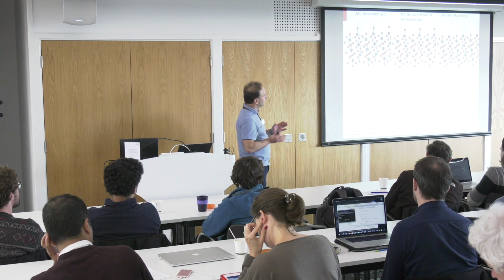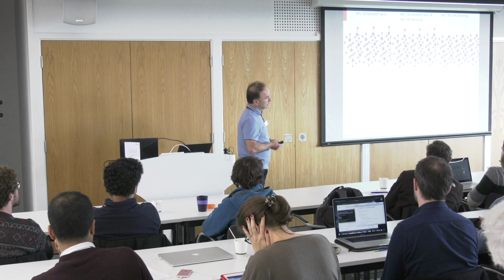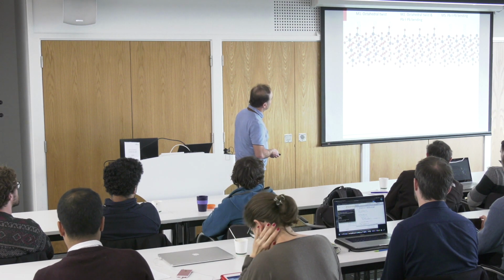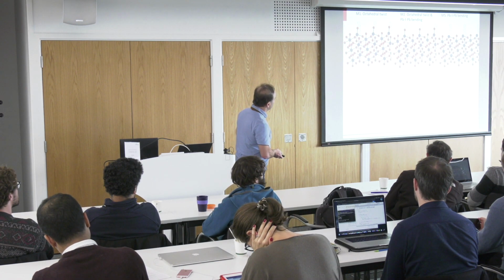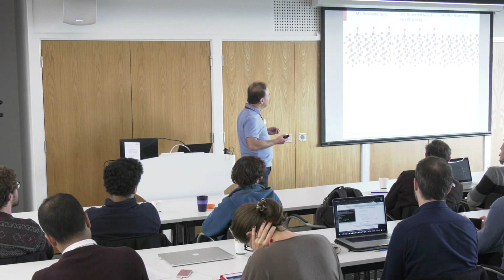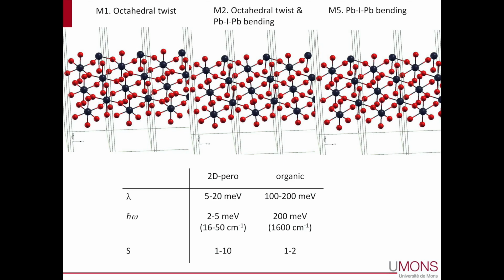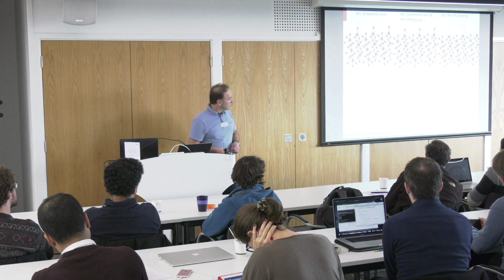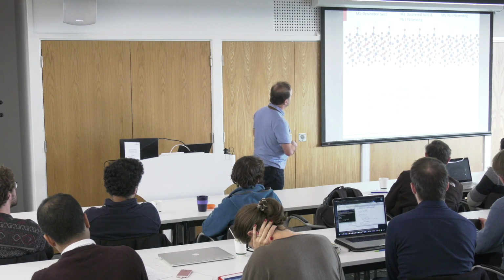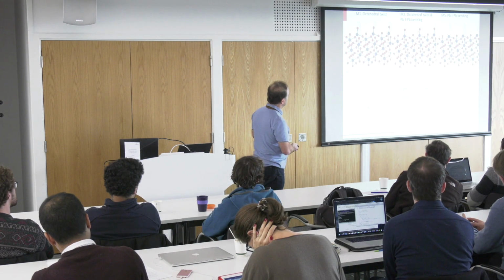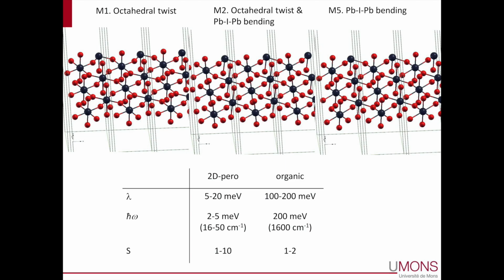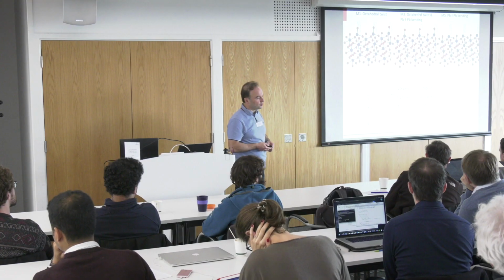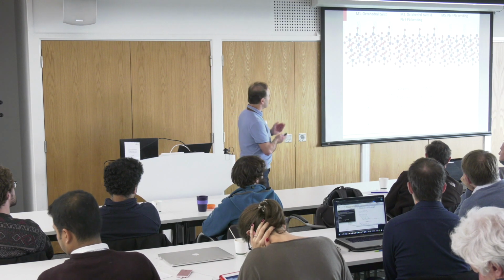So those modes essentially involve distortion of the octahedral configuration of the light inorganic system. And so those distortions, if you think in terms of displacement along the coordinates, are substantial. So we talk about Huang-Rhys factors to quantify this. So the Huang-Rhys factors are pretty large. But of course, since we know we're dealing with systems where the reduced mass of the vibrations is much, much larger because this is lead and it's not carbon, then the frequency is also much smaller, and the reorganization energies are typically one or two orders of magnitude smaller compared to organics. So polaronic effects are rather subtle in those systems.